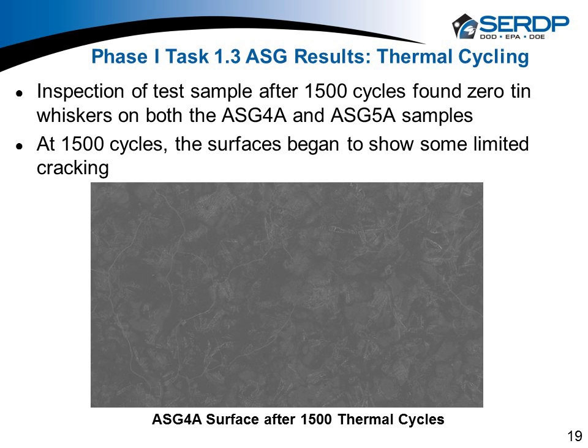One other thing to report on a phase 1 was the thermal cycling. We did 1,500 total cycles. That's what's called out in the industry specifications. And again, that was minus 55 degrees C to plus 125 degrees C, and that was about a 1-hour cycle. It's truly thermal cycle, not thermal shock. So we transition at less than 10 degrees C per minute.